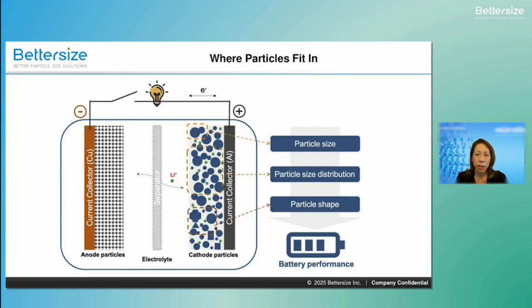The emphasis here is on three main roles: the ionic conductivity, where smaller particles can increase contact area and improve ion flow; packing density, where optimized size reduces voids, and this increases our energy density; and the mechanical stability. Having uniform size will prevent cracking during cycling.